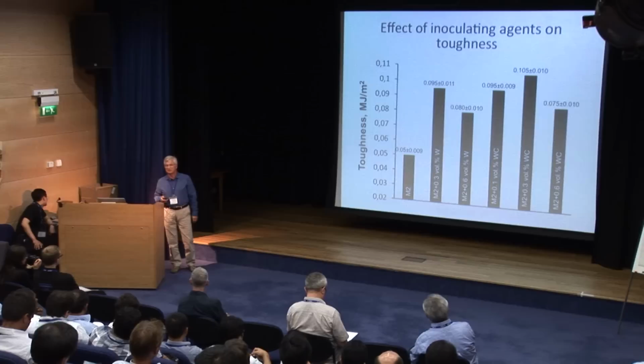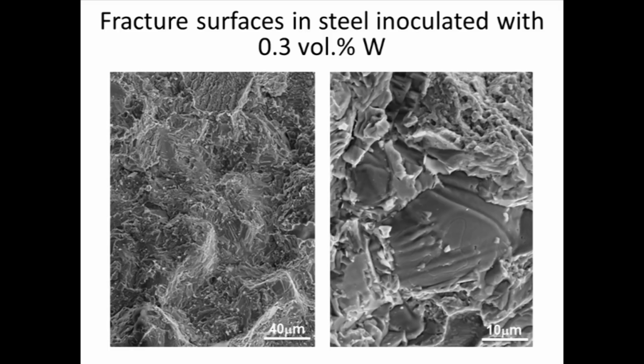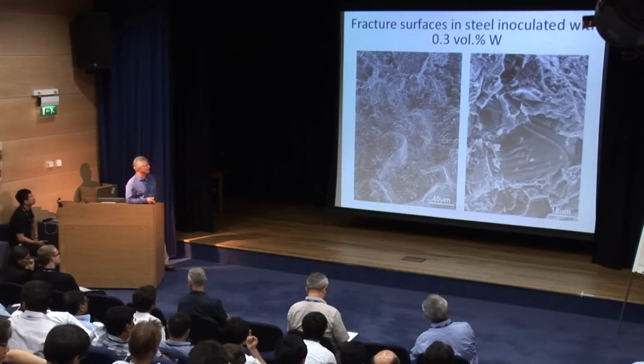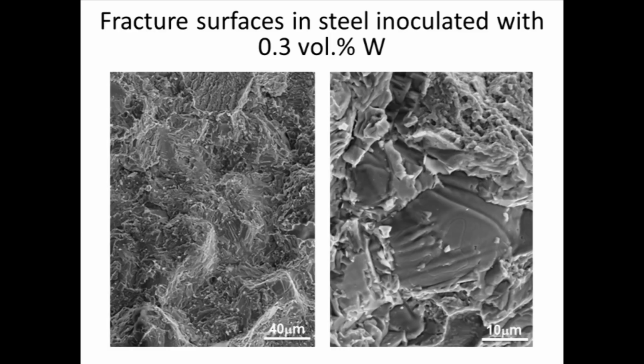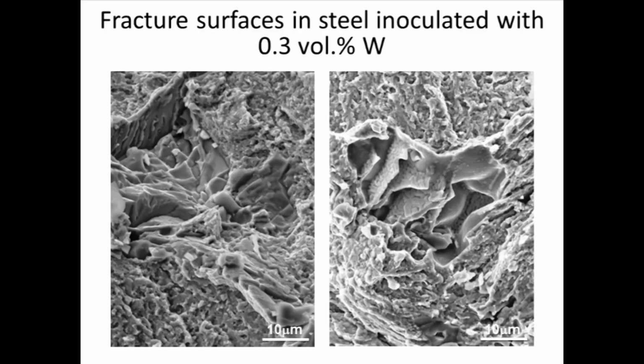This confirms the key role of eutectic carbide in the fracture of cast high-speed steel in the heat-treated condition. Eutectic carbides act as initiation sites for cracks, which are formed as a rule at the carbide-matrix interface by its decohesion. Later, these microcracks initiate fracture that preferentially occurs by a debonding mechanism at the carbide-matrix interface or ends by cracking of eutectic carbides.